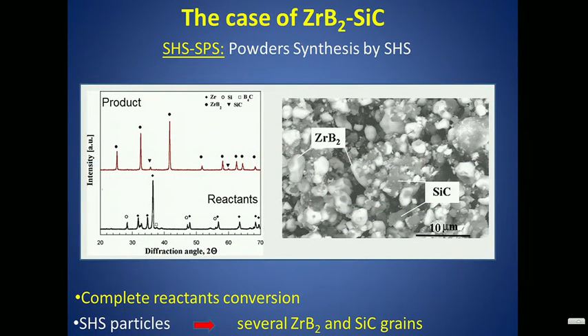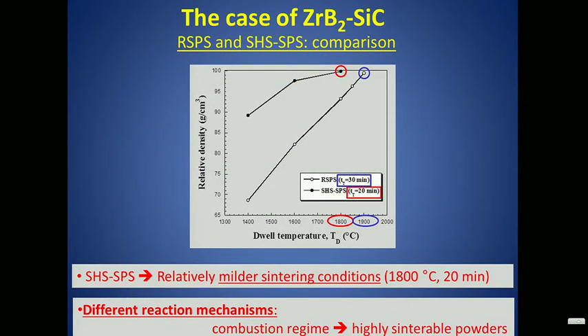product. So this is actually the microstructure of the product. You get the complete reactant conversion, and again, as in the previous case, SHS particles are constituted by zirconium diboride and silicon carbide, which is what we want when we go to sinter. However, if you take a look here, what is interesting to see is that it is definitely much better to go and produce powders by SHS first, and then to sinter them by SPS, because you have relatively milder sintering conditions. Just take a look here to obtain the maximum relative density.